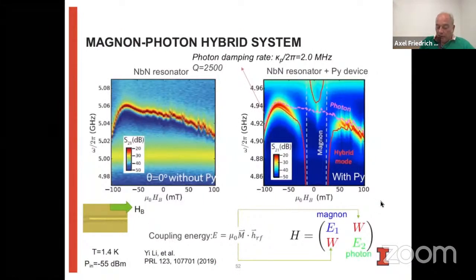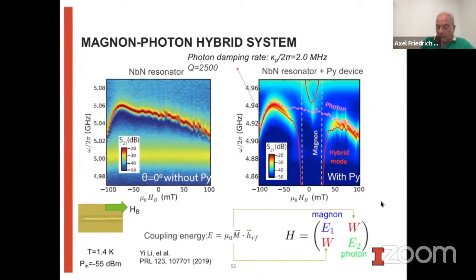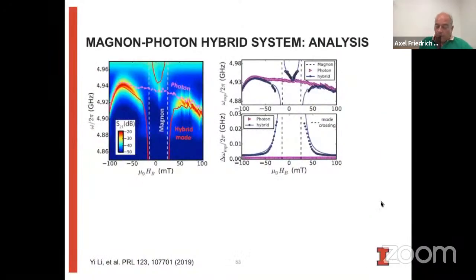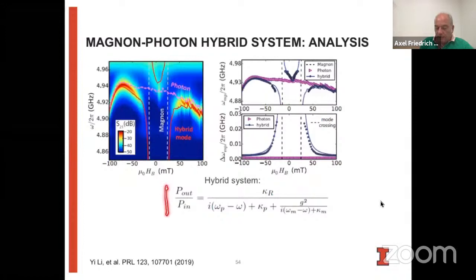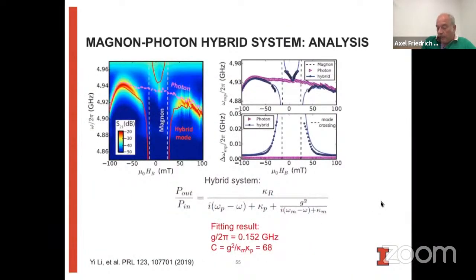But then we can also look at the coupling energy between these two by looking at the splitting. And when we do this carefully, we can analyze the transmitted power using this equation, where we have the decoherence rate of the photons, the decoherence rate of the magnons. We have the frequencies of the magnons and the photons, and then the remaining fitting parameter is essentially the coupling strength here. And when we fit this, we get a coupling of 0.1 gigahertz. And if we calculate now the cooperativity, we get a cooperativity of about 70. Which is pretty remarkably good, I would say.